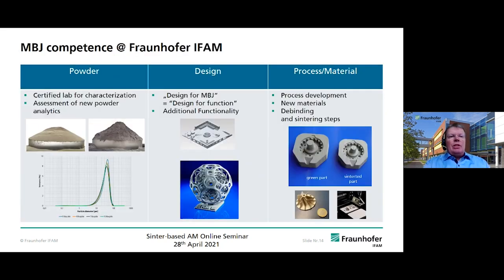Just to give you an impression about powder quality control, we look very deeply into particle size distributions. For example, we work with systems like the CamSizer, which gives us particle size distribution and, at the same time, powder morphology, which are both very important and very closely related to powder flowability, and in this respect to coatability and recoatability of the powder bed.